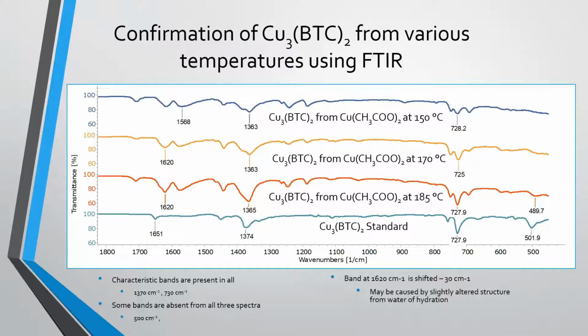Then for observing our temperatures, we found similar results. The 3 different temperatures had very similar bands. Our copper acetate at 150 and 170 were both missing the peak at 500, where the band at 500 was present in the 185 degrees. Again, this is likely due to the disruption of water of hydration, which we were then able to deal with in our highest temperature.